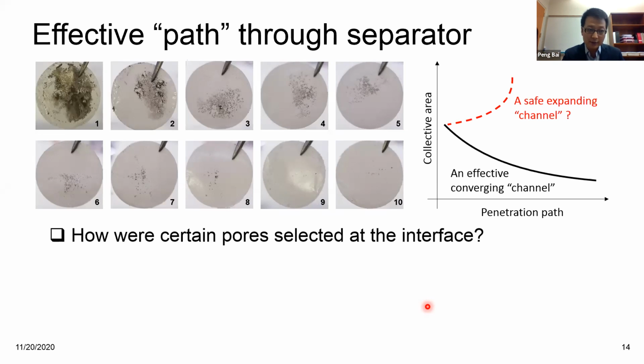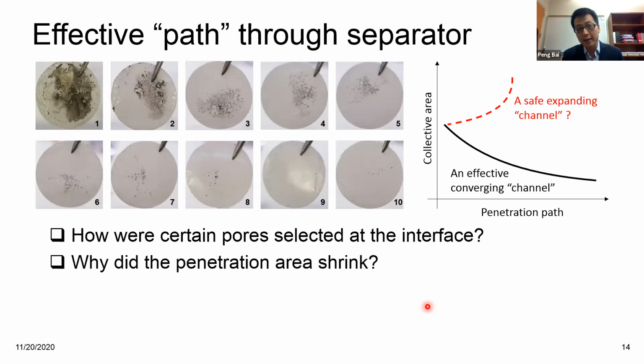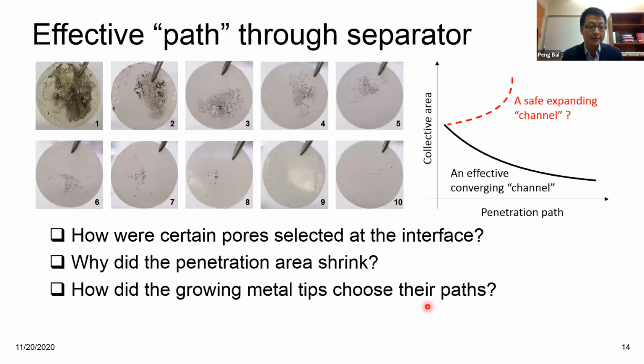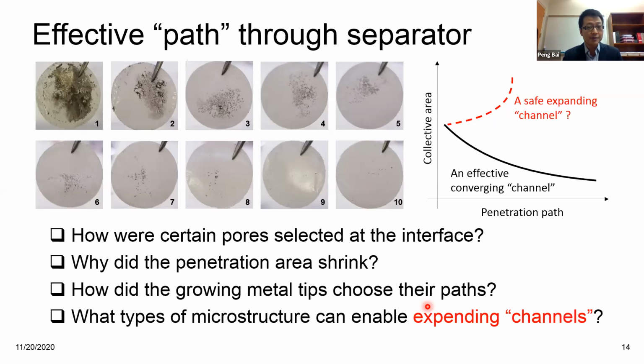So basically, there are several scientific questions. The first one is how were certain pores selected at the interface at the very beginning? And why did the penetration area shrink for this particular case and for many existing cases? Why do we always see this positively deviated exponent in realistic batteries? And then if you think about the microstructure of the separator, when metal tips go through the pores, how did the growing metal tips choose their path? Why did they converge instead of expand? Then the final question is what types of microstructure can effectively enable expanding channels like I drew here. So I think especially for the last three questions, this is where AI can come in to help us design the optimal structure of the separator.